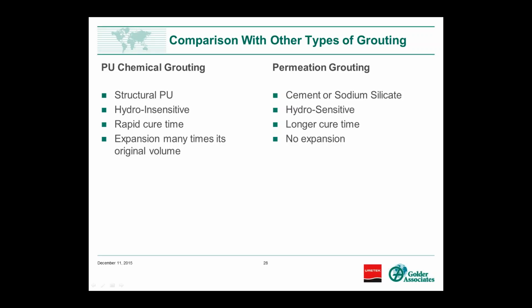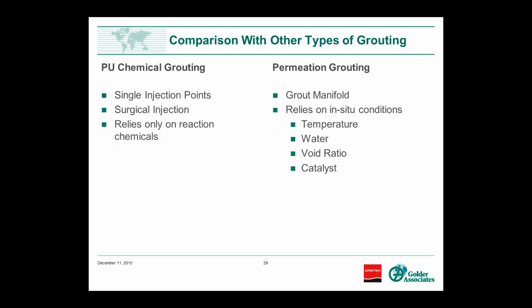I mentioned that you can inject polyurethane in the presence of water. The sodium silicate can get diluted in the presence of water, and if you dilute it below a certain point, then the reaction time won't work, or the reaction may not work at all. The cure time of the polyurethane is very fast. The cure time of the sodium silicate permeation grout is definitely longer. There's no expansion with the sodium silicate or the other types of permeation grouts.